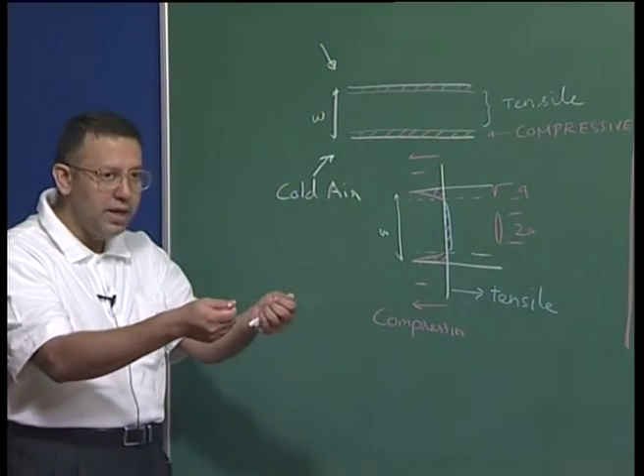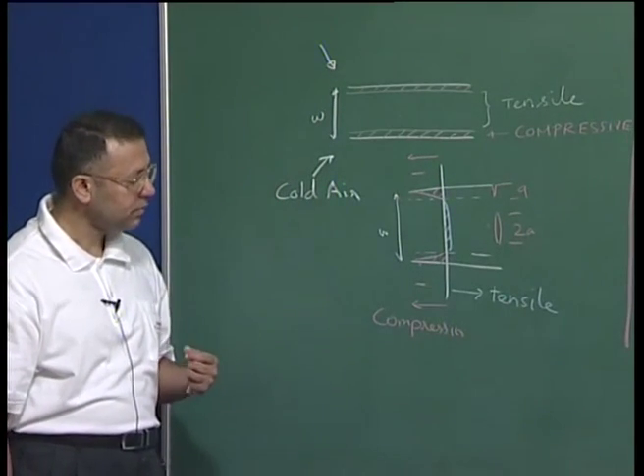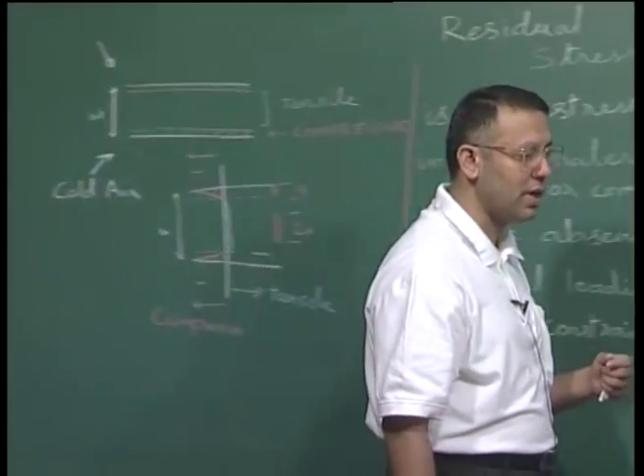So residual stresses are stresses present in the absence of any external agent. They can be detrimental in many cases — leading to warping of a component or even cracking of a brittle body — but if engineered properly, we can use compressive residual stresses to beneficial effect. For the last point: a free-standing body cannot be in pure compression or pure tension overall; one must balance the other so that the body is in net equilibrium.